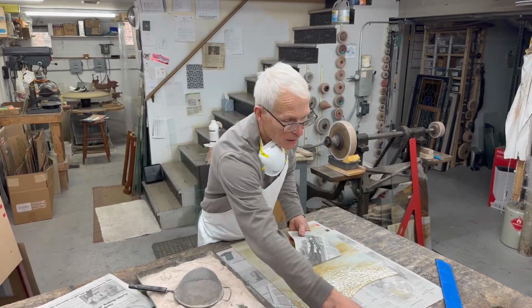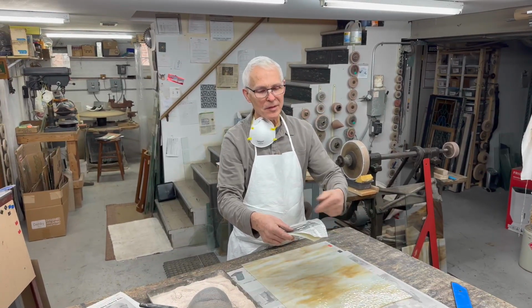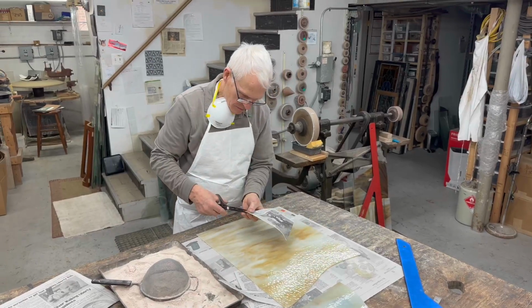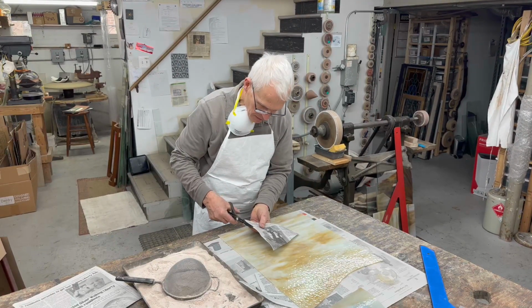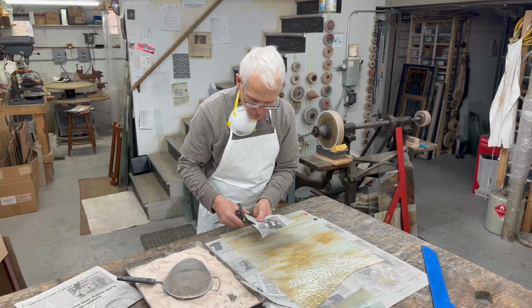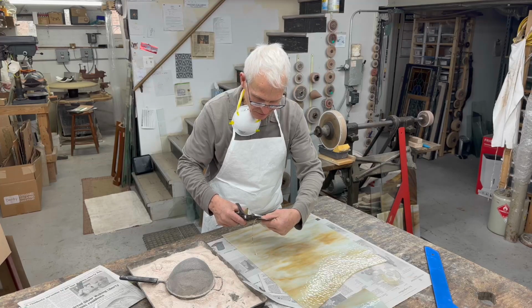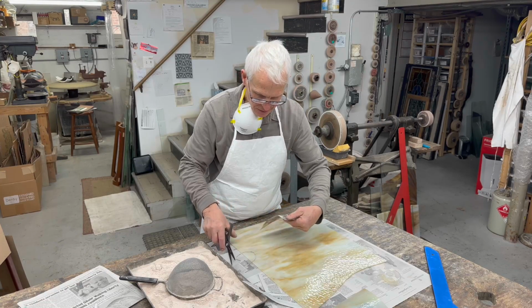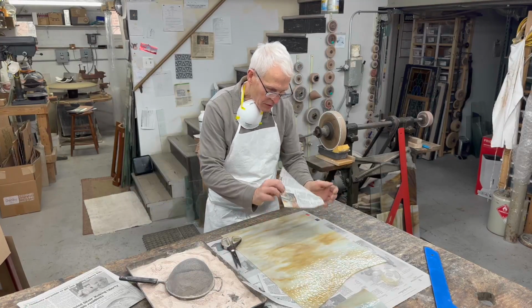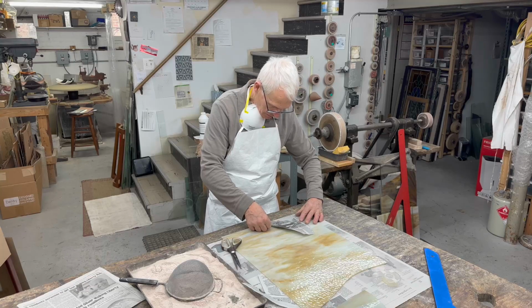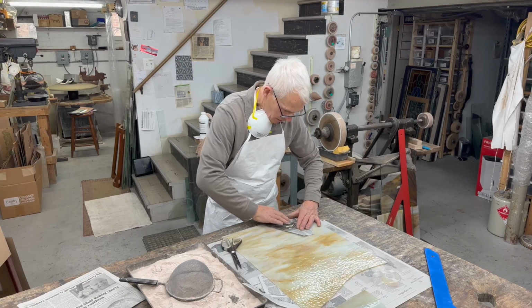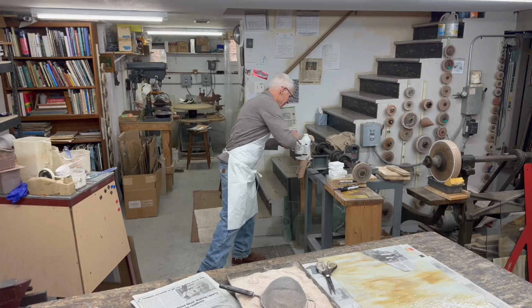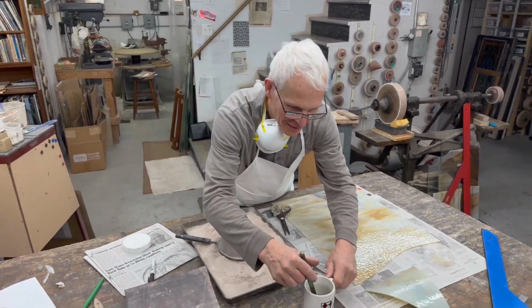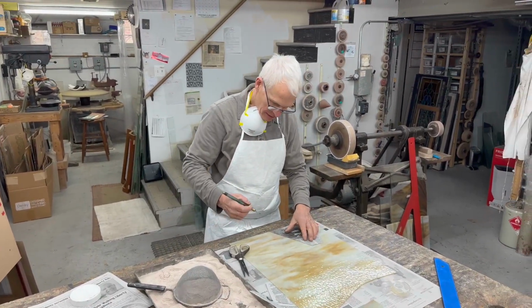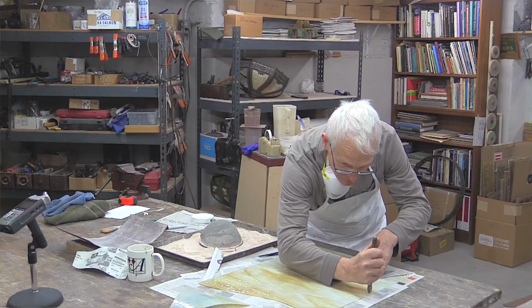Now, one thing to bear in mind: if the pattern was taken over the top of the glass, you'll want to subtract about 1/8 of an inch at the bottom to compensate for the fact that it draped over the top of the bent piece of glass. That way you won't have to grind it down to fit later.